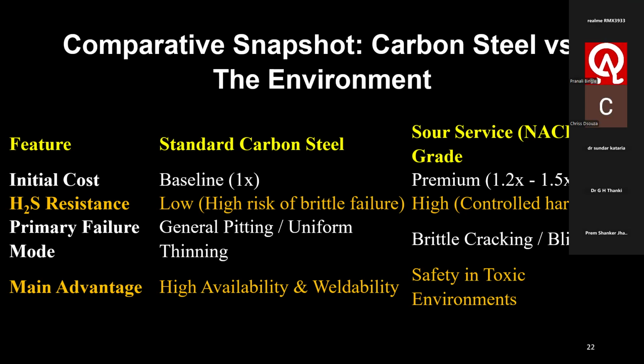The third feature is the primary failure mode. General pitting and uniform thinning in standard carbon steel, whereas in sour grade, brittle cracking and blistering. Main advantage: high availability and weldability, whereas for sour grade, safety in a toxic environment.